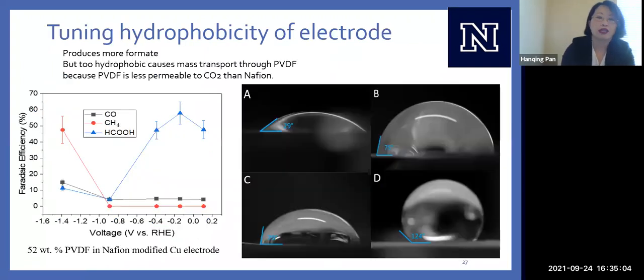So this was really exciting for us. We were able to do this as well. So first thing we did, we can change up the hydrophobicity of our electrode. And we're doing this by mixing PVDF polymer into our Nafion polymer. And keep in mind, PVDF is extremely hydrophobic. So the more PVDF we add, the more hydrophobic we can make our electrode surface.